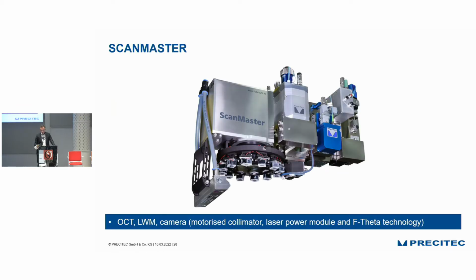The optic we call SCANMASTER. If we have a closer look, then you can see here on the right-hand side a camera, next to the camera the laser welding monitor introduced before, and next to it the OCT technology for distance measurement. And the only take-home message here for you is we measure the distance before welding, the distance to your samples, to your batteries, and give the information to the motorized collimator. So we have here a closed loop between measurement to your samples and readjustment of the focus of your system. This may sometimes be beneficial in the field of battery contacting.